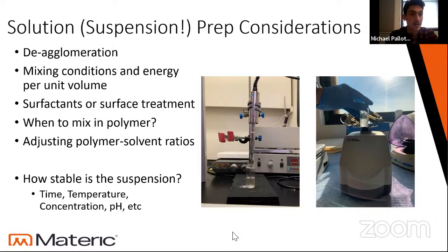When adding an additive and creating a suspension or an emulsion, the prep for the solution is just as, or in some cases, even more important to make sure that that goes well. I say more important because your spinning could go well, but if your nanoparticles or your additives aren't dispersed correctly or prepped correctly, your final product still might not function the way you had intended. So we start to combat some of the issues we run into with additives via, I'll explain via these bullets.